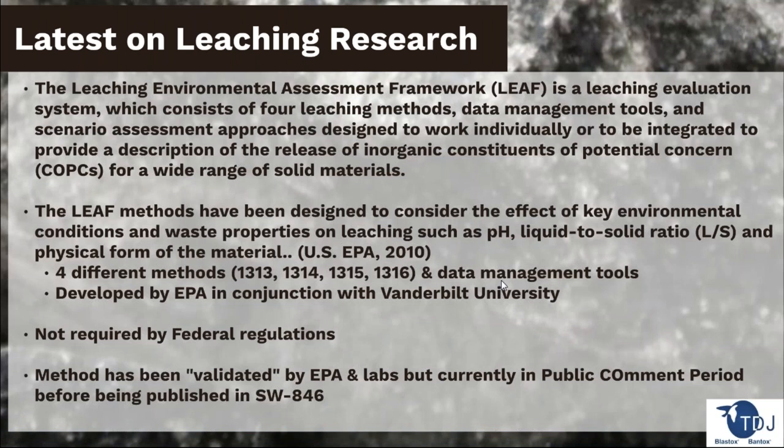This last slide covers the latest leaching research. There's a protocol called the Leaching Environmental Assessment Framework, or LEAF, developed in collaboration with Vanderbilt University and the EPA. It involves four different types of leaching methods based on what you're trying to accomplish, and changes things such as the liquid-to-solid ratio and how pH is adjusted during the actual test itself. It's been validated by EPA but hasn't been published yet because it's still in public comment period. You'll want to familiarize yourself with it in case it becomes mandated in the future. This test is pretty expensive — we've heard between five and ten thousand dollars per test, compared to about two thousand dollars for MEP and 150 to 200 dollars for TCLP and SPLP.